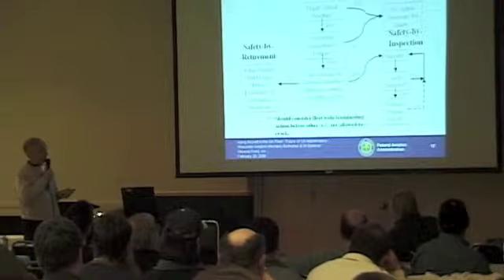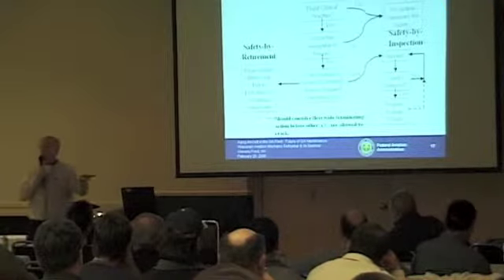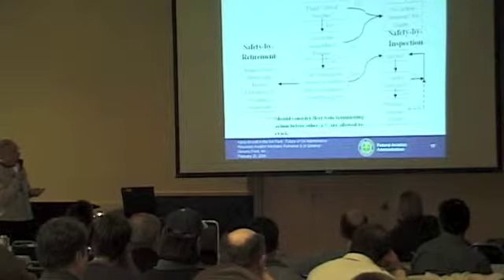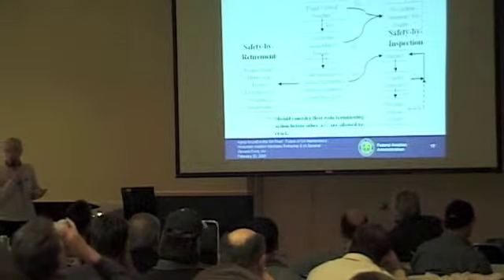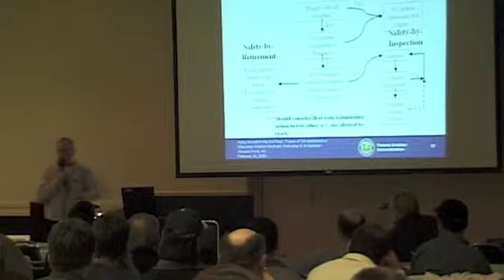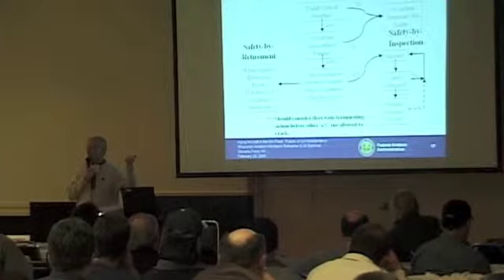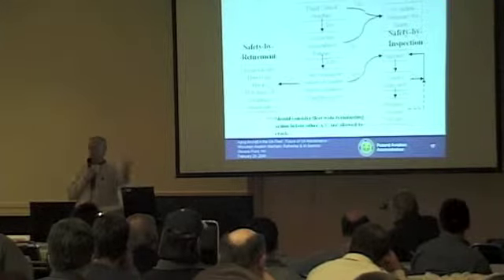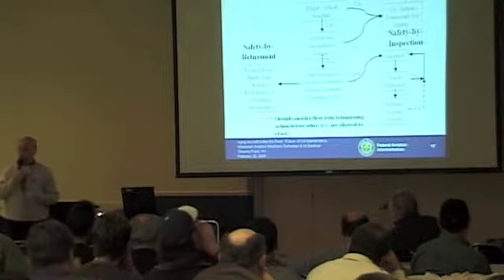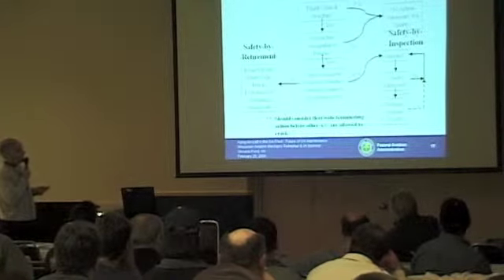If we can't reliably detect it, and this would be the 402 situation, the Cessna 402 situation, because the crack was too small. We couldn't find it in time, right? So we've got to modify or retire. So the modification of that was that wing strap, which in effect retires that wing there because the stresses in the wing spar itself go way down with the strap. I think there's a repetitive inspection in the AD every 20,000 hours. They have to go inspect that. So we've basically given another 20,000 hours to the 402 by modifying it. So we've got some of those 30,000 hour guys will be 50,000 hours. When will that be? So we can do that.